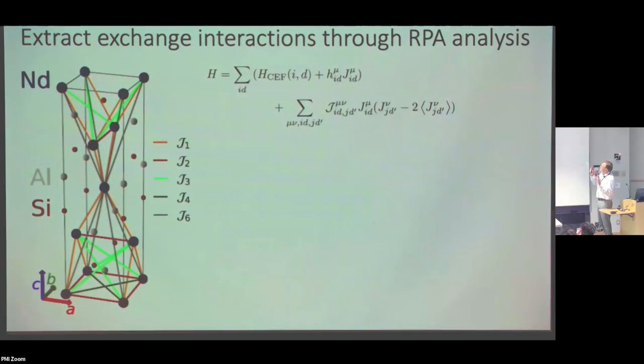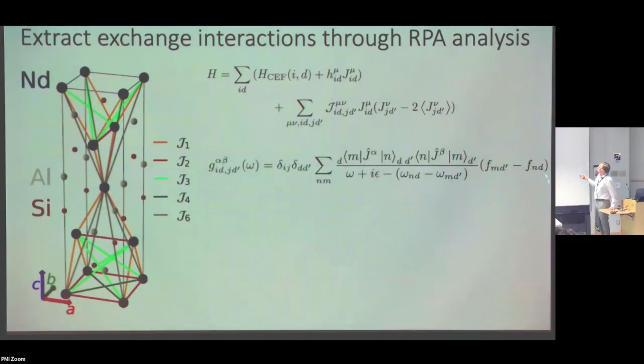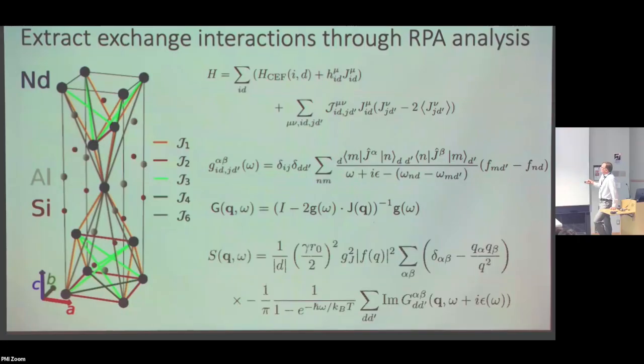And so that requires this random phase approximation calculation that will include both the crystal field Hamiltonian and the exchange field. Sorry, this term is the exchange interactions, and that's the mean field component. And we'll both have the Z part, which does the overall splitting, and then the transverse part that does the dispersion. And this is all treated using Green's function analysis in random phase decoupling. And we end up with this expression for the full dynamic correlation function. So it sort of comes back to what I was saying in the very beginning of the lecture, that we're able to directly calculate the scattering cross section and make comparison to the data.